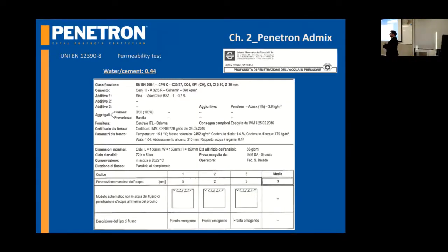I know that tests and numbers are your job, but I want these tests to be looked at in another way. This is a permeability test with a concrete with a water cement ratio of 0.45, 0.44, sorry, and it has a penetration maximum of 3 millimeters. This is another permeability test with another water cement ratio that is 0.58, and you got a penetration maximum average of 9 millimeters.